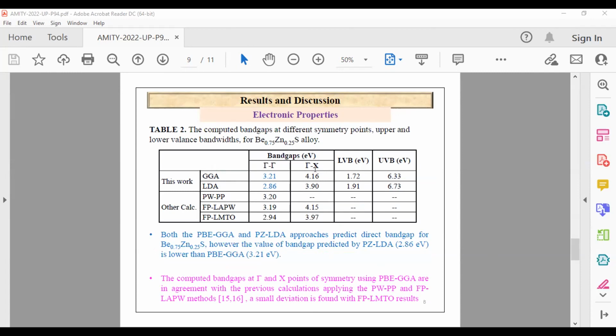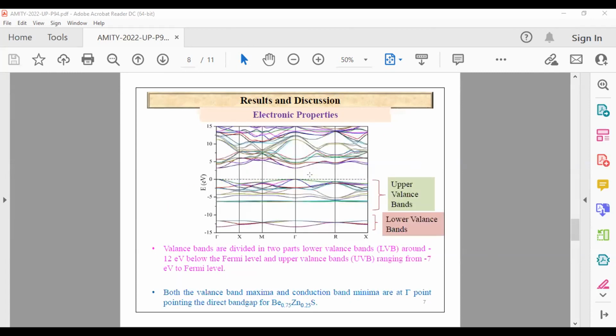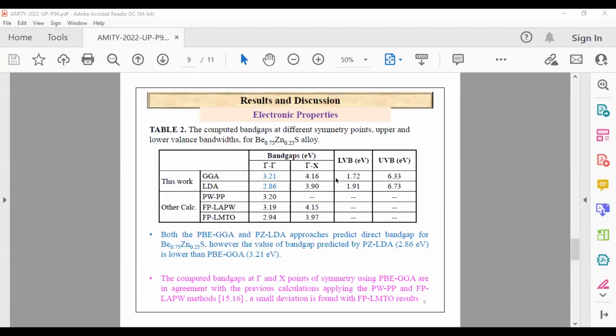And for other points like gamma to X point of symmetry, we find a higher value of gap. So this is a direct band gap semiconductor. The lower valence bandwidth is 1.72 using GGA, and using LDA we obtained 1.91. The upper valence bandwidth for GGA is 6.33 electron volt, and for LDA we obtained the value of 6.73 electron volt.